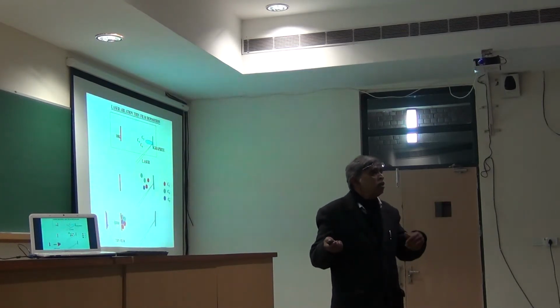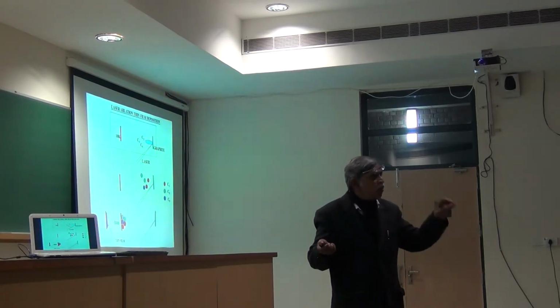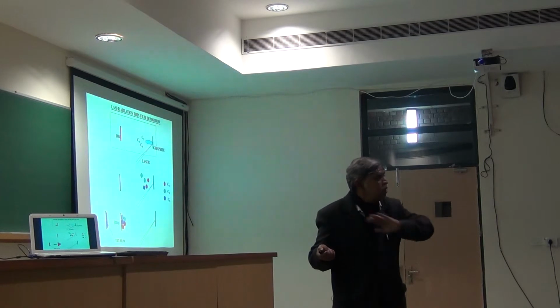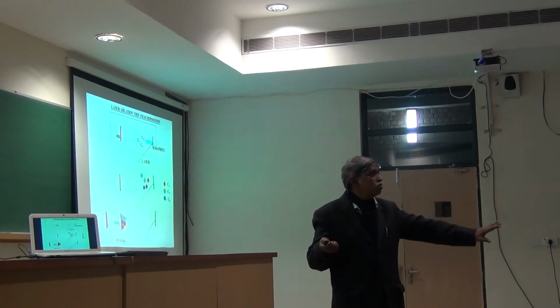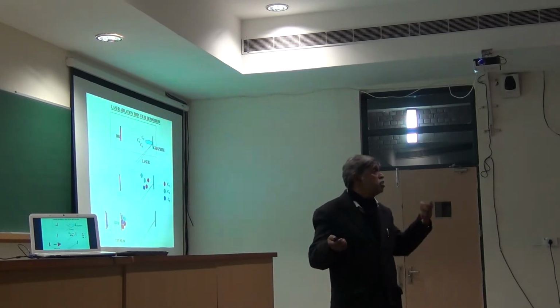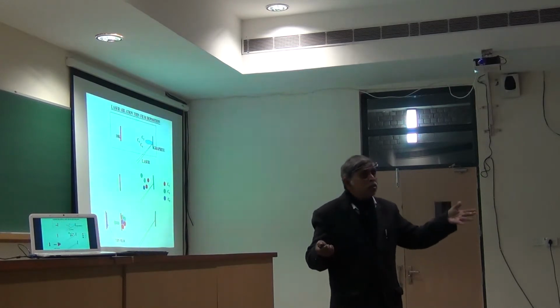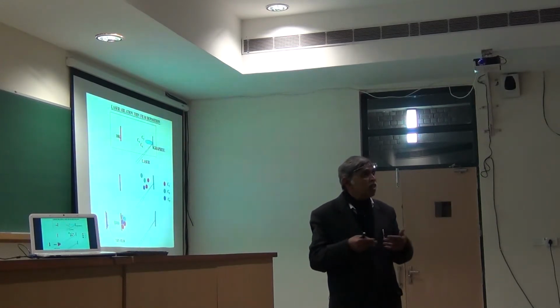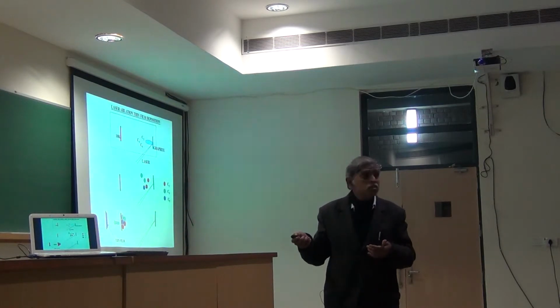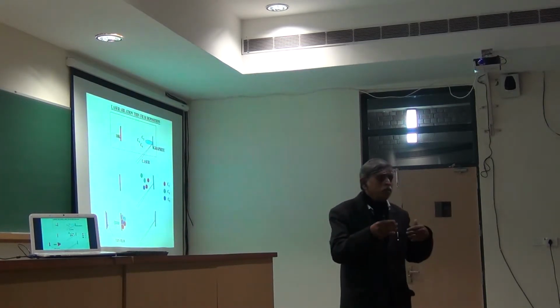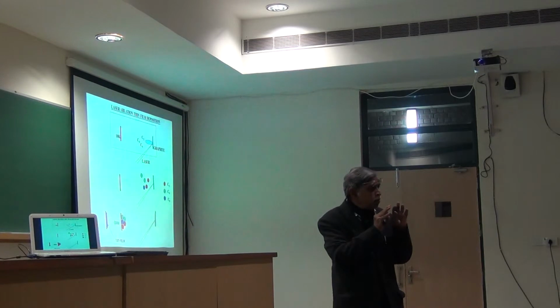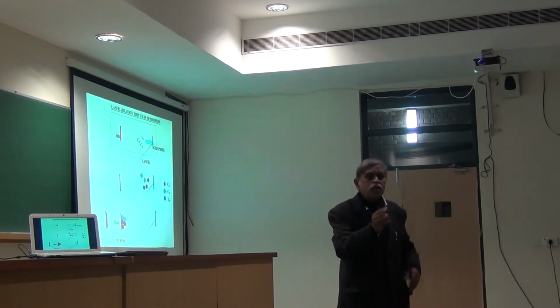So what we are doing is very similar to a thin film deposition, except that we prevent the formation of the thin film by supplying a sufficient amount of argon, so that you don't have these reactive species reacting. The precursors to these thin films are actually trapped in these argon beams, so that you can study what is being produced as a result of the laser ablation. So there is something very common, but the presence of argon is what sets it apart.